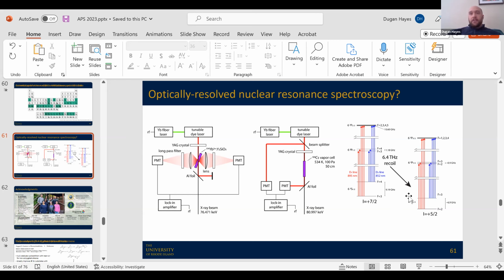And so we could do essentially step scanned high resolution optical spectroscopy on the nuclear excited state of cesium-133. And by measuring these optical transitions, we can then correlate them back to get the isomeric shift, and then also from there figure out our nuclear transitions.